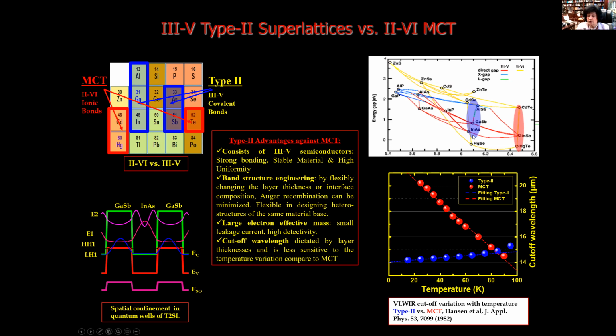Now, if you come to the type-II superlattices, aluminum antimonide, gallium antimonide, indium arsenide, or indium antimonide, they are III-V, and at the same time we have the gallium antimonide or indium arsenide substrate with high quality and larger size, and that III-V semiconductor is very, very stable.